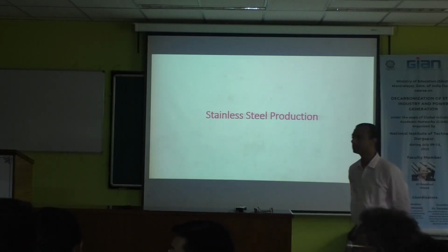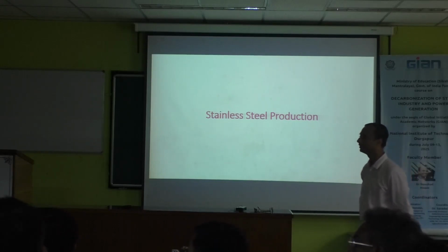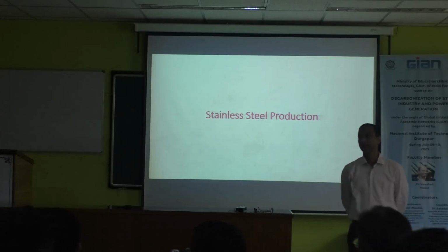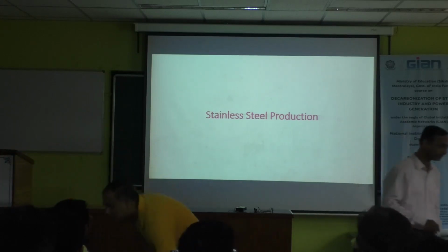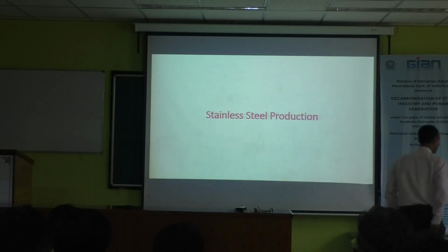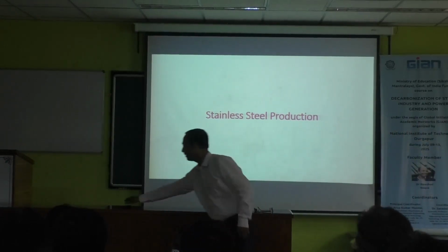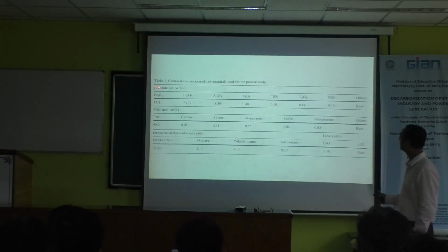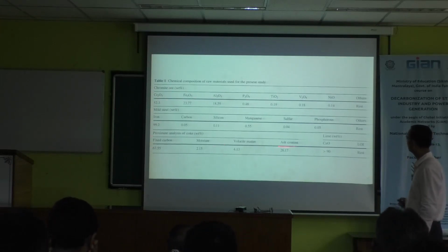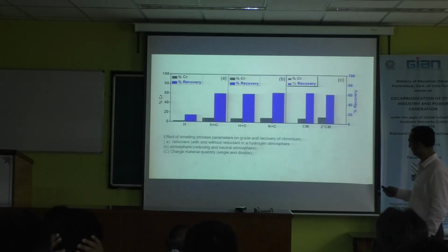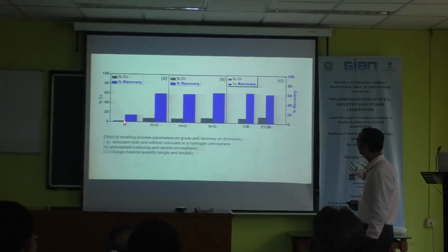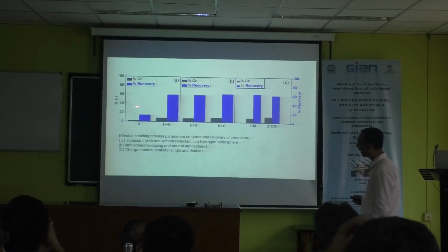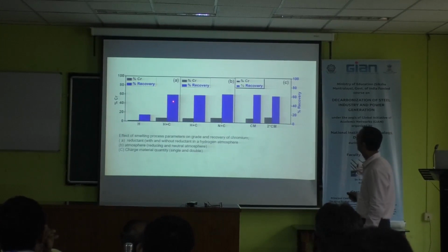Then the question will come: what will happen? We have prepared a Cr2O3 overburden mix. It contains 52.3 percent Cr2O3 and Fe2O3 was 33. Then to adjust the composition, mild steel is also there. Then we have prepared different mix compositions. If you see here, chromium recovery in case of only hydrogen plasma, and hydrogen plasma plus charge containing carbon.